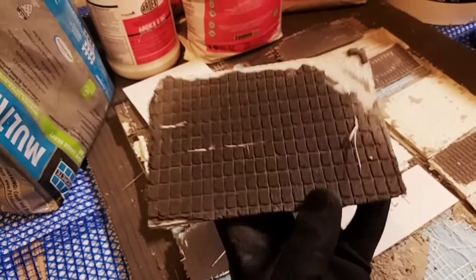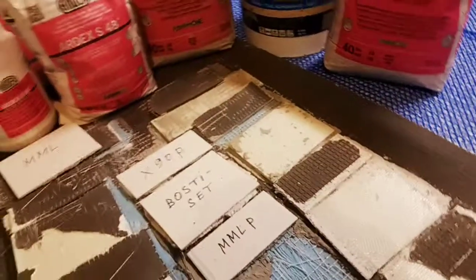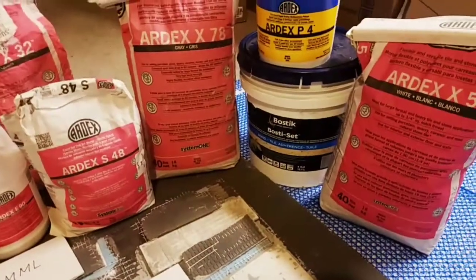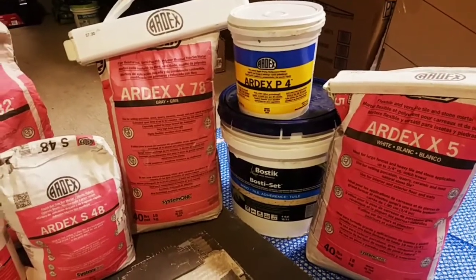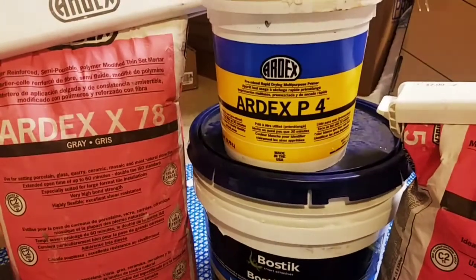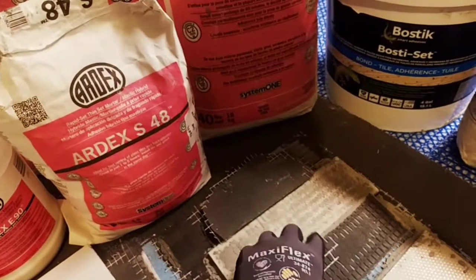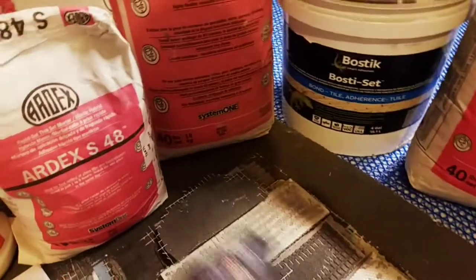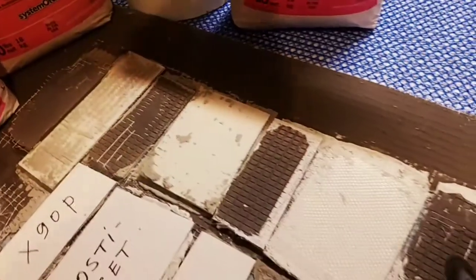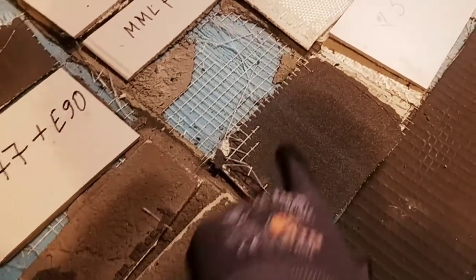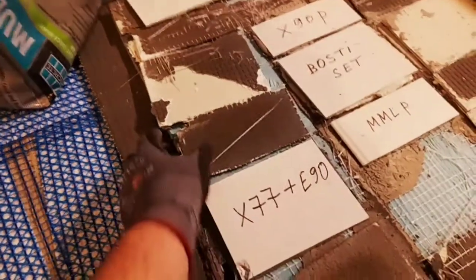And as you can see, it provides great bond with resin-backed tiles. But also in my test, I want to point out that even though at this point Ardex does not specifically recommend Ardex P4 as a primer suitable for resin-backed tiles, these results after a 7-day shear bond strength showed such a great adhesion. Sorry, this was not primed. This is primed P4. It shows great results of how cementitious mortar bonds to the back of the resin-backed tiles that is treated with Ardex P4.